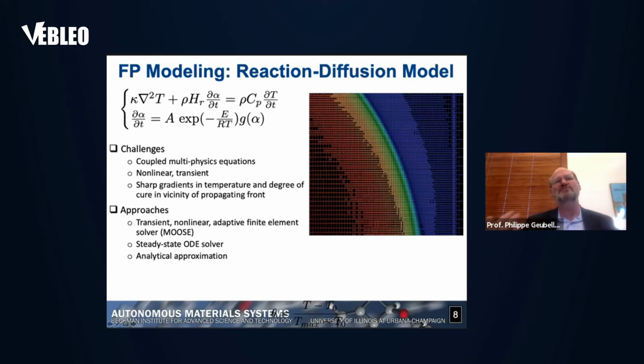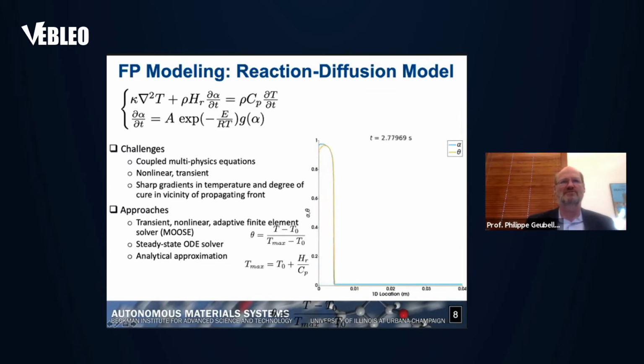From a purely theoretical point of view, the challenge is obviously that it's a multi-physics coupled type of equation. You have to solve for both temperature and degree of cure. It's non-linear and transient, but the most difficult part is the fact that you have very sharp gradients. We adopted 3 different approaches to study this. The most costly, but the most detailed one, is based on the finite element solver. We use the MOOSE environment developed by Idaho National Lab because it has a very robust mesh adaptivity capability. We've also written what we call a steady state solver, which transforms these partial differential equations into ordinary differential equations. And finally, the analytical approximation that I'll describe.